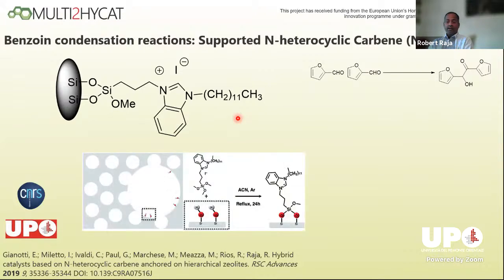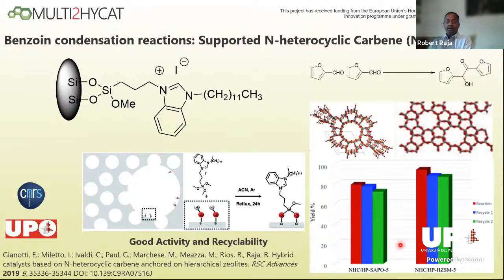So our partners in Alexandria had a slightly different approach as to how they made these hierarchical systems. So we followed the soft templating approach. So we went bottom up, whereas they had a hard templating strategy where they went to a top-down approach. So they took conventional zeolites, in this case, this zeolite, and we contrasted that with an aluminosilicate analog, which is the SAPO5 analog, of which I showed you an analogous